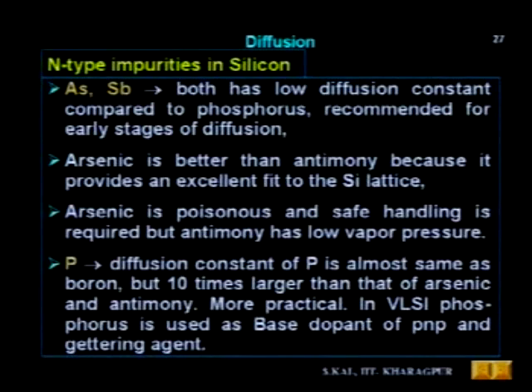Arsenic is better in comparison to antimony. The reason is that arsenic provides an excellent fit into the silicon lattice compared to antimony. Although both arsenic and antimony have lower diffusion constants, antimony is not favorable compared to arsenic because arsenic has an excellent fit into the silicon lattice. But one of the problems with arsenic is that it is poisonous, and you require safe handling of that material compared to antimony. On the other hand, antimony has low vapor pressure compared to arsenic.